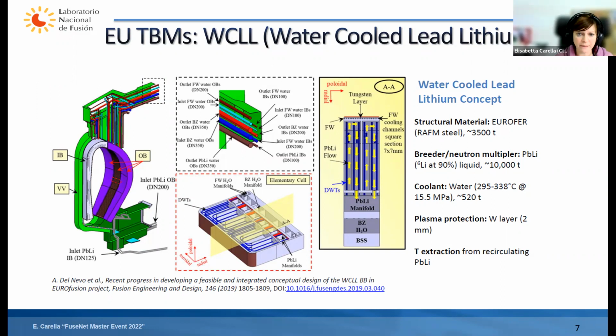The first wall protecting the plasma is always tungsten. The structural material is always Eurofer, but in the case of breeder and neutron multiplier, we will use lead lithium with an enrichment in lithium-6, for the reason that I explained in the first slide: we need a higher content of this isotope of lithium to produce an exothermic transmutation reaction. In the case of this TBM design, it's also really important to extract tritium from the recirculating lead lithium.